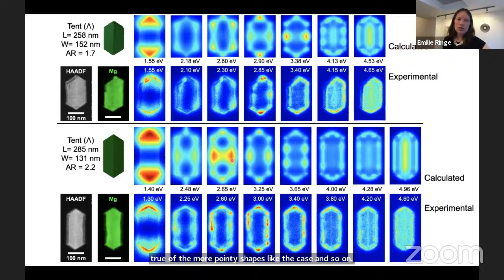So yes, we do expect a strong change in reactivity for these particles. We do expect a strong change in thermal response of these particles. We expect a strong change in refractive index sensitivity and so on when going from one mode to another, because that field localization is different. And this has been shown for a number of structures in gold and silver. The beauty here and the difference here is that the shapes we can access are really different. And funnily, and again, that's another paper we're writing at the moment, these are basically folded shapes that are sharp everywhere. And so we do get quite a bit of an electric field in that fold, as well as at the tips of these particles, depending on the mode. So yeah, it does give us a real knob to turn in terms of reactivity and of sensitivity.